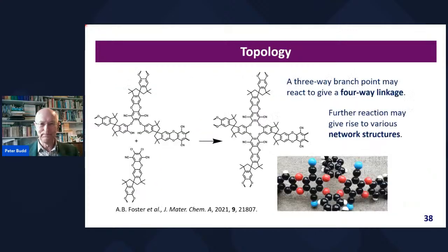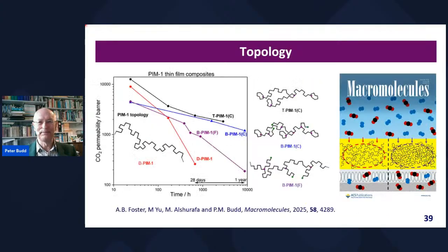And if we get this branch with this sort of structure, that can actually go on to react further if you push the polymerization longer, creating a four-way linkage. And the consequence of that is that, again, if you push the polymerization for longer, you can start to build up network structures of different types, all of which have an impact on the permeation properties.